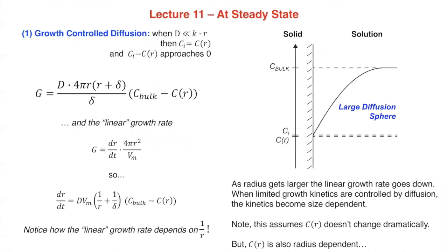Diffusivity is really, really low, and so the monomers take forever to get to the crystal surface, and that process is so much slower than any kind of attachment that it's really all about diffusivity and has nothing to do with the attachment. As soon as they reach the crystal surface, for all practical purposes, they attach.